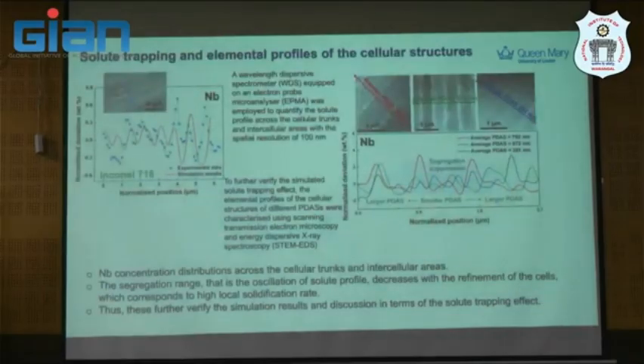And we use this to validate against the wavelength dispersive spectrometer in the electron probe microanalyzer, EPMA, here. You want to validate or verify your model with this segregation profile across, experimental and simulation, to make sure that your model is predictive enough to do something further. And this is only the niobium profile. After that, you look at different locations of the melt pool and try to extract the dendrite arm spacing at different levels, because this is the spacing at which the segregation profile takes place. So a summary of this is that the niobium concentration is distributed across the cellular structure, the cellular trunk here, and the intercellular area.